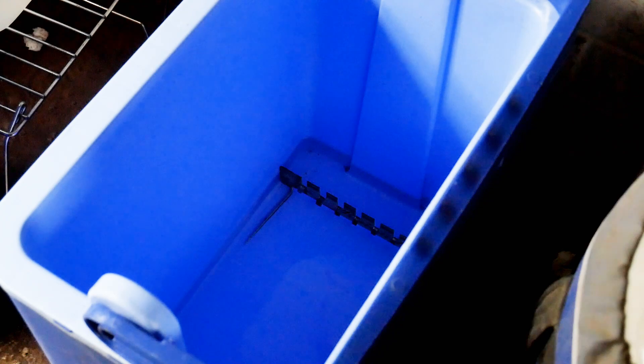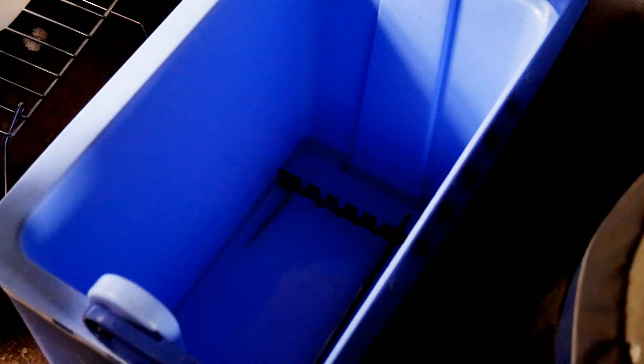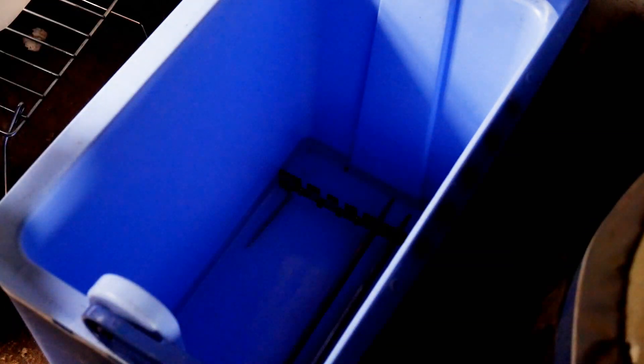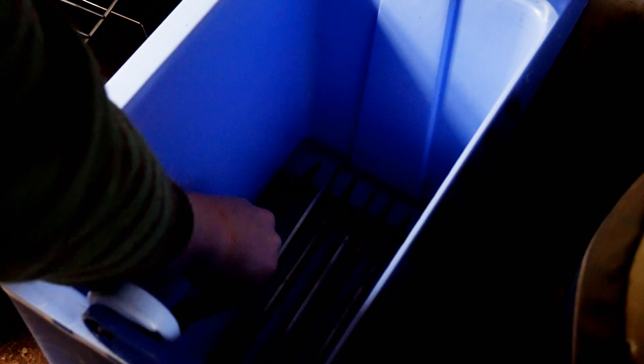Well, I've measured them all on the Rockwell hardness tester and they're all coming out around about 61.5 to 62 HRC. So I'm now going to put them individually in a rack, specially made rack. It's only a simple thing to hold them separate, and this will allow the CO2 dry ice to cool them equally on both sides. At the moment there's no CO2 in there, just isopropanol alcohol—rubbing alcohol, basically.